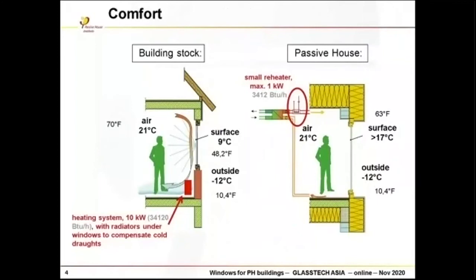The other point is about comfort. If you want to have a good thermal comfort inside your building, your opaque parts, but as well, and most importantly, transparent parts such as windows and glasses should be well insulated. Therefore, we need 3-pane glazing so that the minimum surface temperature at the glass is, in this example, better than about 17 degrees centigrade, even if it's very cold outside. In old, conventional buildings, this glass and frame insulation is not so good, and therefore you need a radiator just beneath the window.